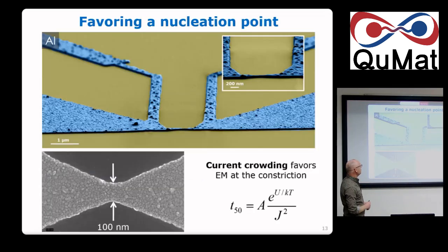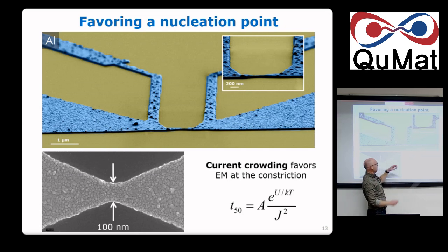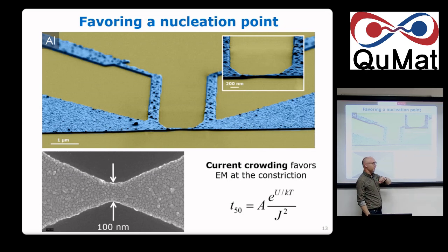So the first thing we need to do is to know exactly where we are going to electromigrate. And it happens there is a big, very well-known law that is called Black's law. It says that if you make 100 devices, 50 of them will fail due to electromigration with a time to failure, which is given by this equation, which involves activation energy, temperature, and the current density. So if you want to make them fail quickly, just increase the temperature, reduce the binding energy between neighboring atoms, or increase the current density. Okay? So we play with that.